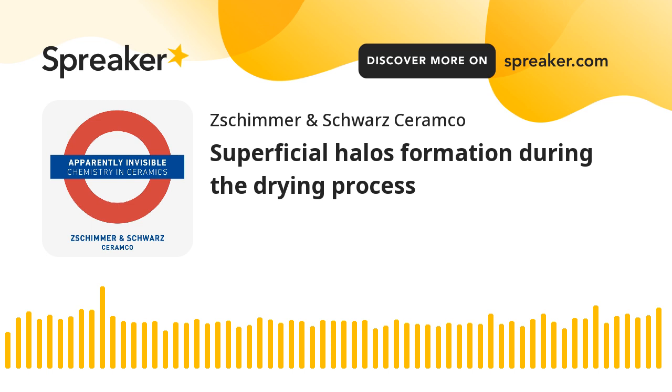In this respect, even if the water electrical conductivity is not a guideline to precisely identify or classify the kind of anions within the water, the check of its values, of the electrical conductivity of course, can however give you information about a possible high content of ions. If this happens, it is usually possible to act by cutting the processed water, that means adding mains or groundwater to reduce and decrease the action of the ions.